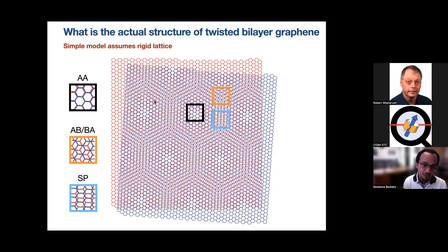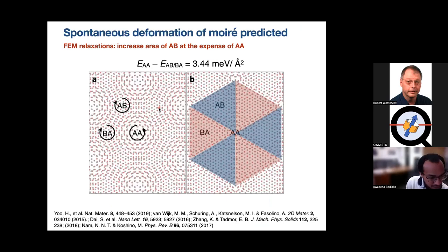And to understand that, we've got to switch gears a little bit and think about what the true structure of twisted bilayer graphene is. So the simple model I showed you assumes that the lattice is very rigid, okay? And that you have this gradual transition between one stacking orientation and another. But it turns out that finite element simulations and electron microscopy data, which I'll show you in the next slide, suggest that there is a relaxation process that entails a series of local rotations. This Nature Materials paper from 2019 is actually work from Philip's group. Hyobin and Rebecca did this work,